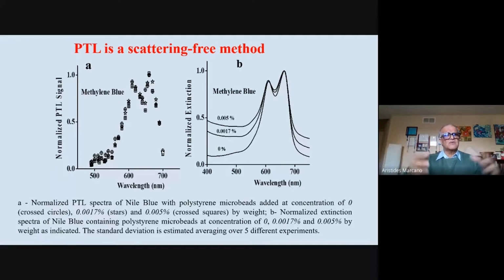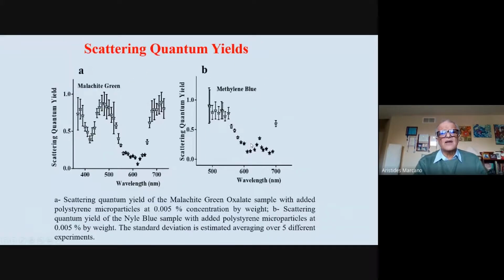So they have some real media. They have a lot of things inside, they are turbid, they can have some turbidity, but still you can get the absorption despite that turbidity. If you do the typical absorbance, you see big changes just because of this increased scattering, and you can actually measure the scattering quantum yield. You can see it's another spectrum. It's a little bit noisy just because we are using a lamp. But if you do that with the laser, this is going to be very, very good and very easy to do.